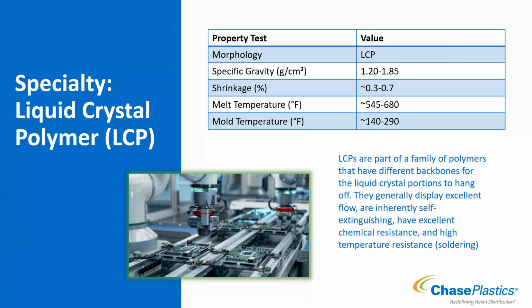LCP, liquid crystal polymer or liquid crystalline polymer, I've heard it both ways. Its morphology is neither semicrystalline nor amorphous. Semicrystalline materials, having their crystal structure, when processed and in the molten state, do not have any crystallinity left to them - they're all amorphous when molten. That's why when it shrinks and tries to get back to its crystal structure, that's when your crystallinity starts back up. LCP, on the other hand, has sections that remain crystalline even at the molten state, maintaining its crystal structure in those areas. So it kind of has its own morphology, it doesn't really fall into one or the other.